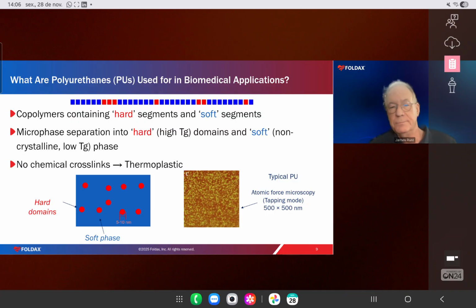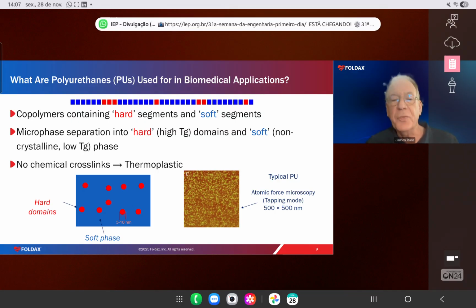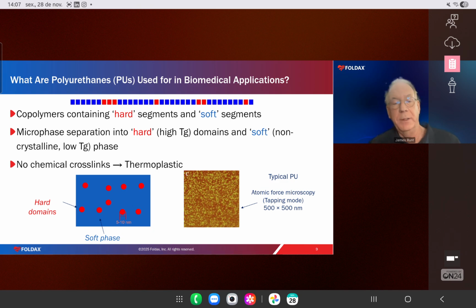And when you manufacture this and you create a solid material from it, what happens is the hard segments segregate away from the soft ones. And so you end up with a structure, it's called microphase separation, but it's actually nanoscale phase separation. If you see the cartoon on the lower left, the red dots there, and they're certainly not uniform in reality, they're on the order of nanometers. And the blue continuous phase is flexible. So you end up with no chemical crosslinks, with thermoplastic hard domain crosslinks. So in principle, you can melt the material, certain materials, and reformulate.